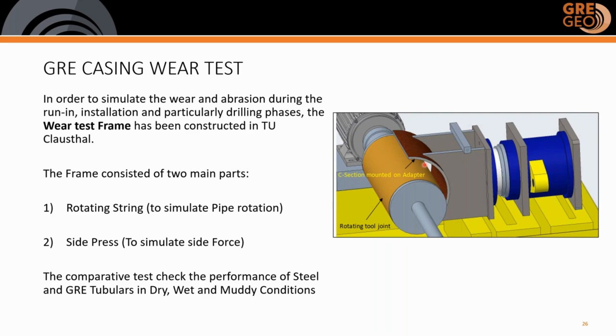So I hope I answered your question regarding the wear test. Regarding shock loads, no, we didn't simulate shock loads. What we really take care of is to define a drilling program that will give you enough room to avoid getting stuck. And although you may get stuck, what we also found after this wear test is that the friction factor of this material is much lower than that of the steel casing, which will help you remove the pipe with lower loads in case you get stuck. Also, this is a lighter material. So whenever you lose control or run your casing into the well too fast, the shock loads will not be dramatically high. This is our expectation.